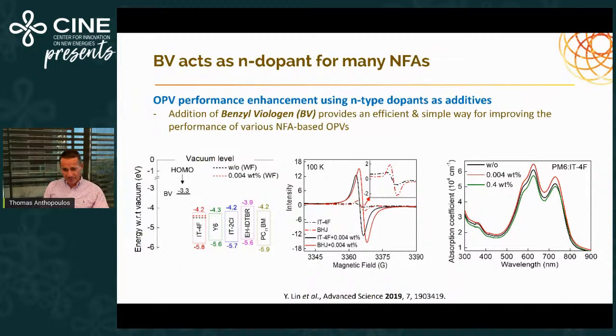Before we essentially make the devices, we realized that we see an N-doping effect. We see what appear to be a generation of free electrons because of the presence of the BV, but we also have seen an enhanced absorption across the layer. It appears as if the layers were getting more dense, if you know what I mean.